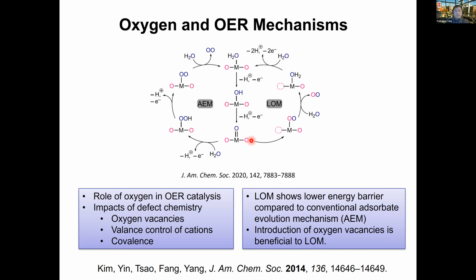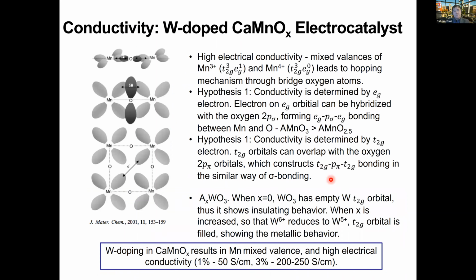So with that, I'm going to continue looking into what other factors we can tune to enhance the performance. One of them, of course, is the conductivity argument here. One of the systems we tested uses tungsten as a dopant in, for example, the calcium manganese system. Why we choose tungsten as a dopant is that we try to see whether we can change the structure by having a certain amount of dopant and change the manganese-oxygen overlapping and the configuration. So there are two different considerations here: hypothesis 1 and hypothesis 2.